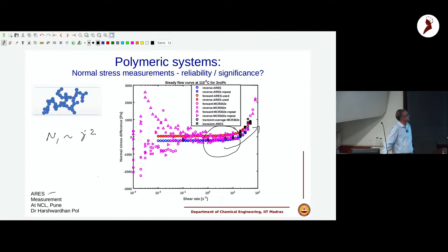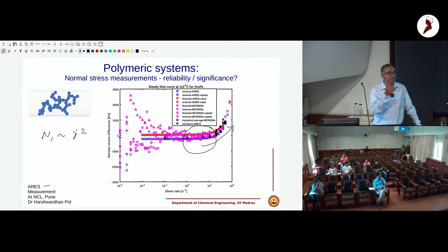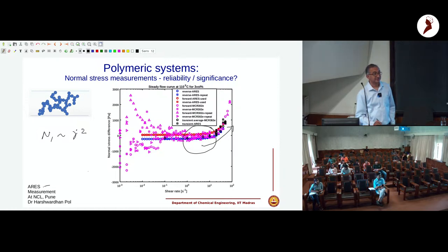So because at high shear rates, presumably the structures are broken. So that's why the thixotropy and the structure building and breakup may not have, which, if you look at this data primarily, it looks like that. But we've also looked at the transients. See, this sometimes cannot give us full information about thixotropy, right? So ideally, what we would like to do is to do a startup shear and then look at the evolution in normal stress as a function of time to really examine thixotropy in more detail. So which is what we have done, and now we are also trying to model that and put the two together to, you know, evolve an understanding. Because this does seem like that, yes, there is normal stress signature, but it is due to particle polymers being there and not due to this structural evolution.